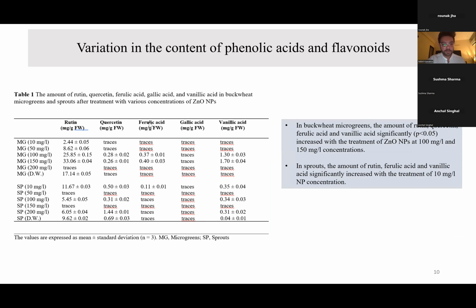After this, ultra-performance liquid chromatography was performed for the analysis of rutin, quercetin, ferulic acid, gallic acid, and vanillic acid. Talking about microgreens first, the amount of rutin, quercetin, ferulic acid, and vanillic acid significantly increased with the treatment of nanoparticles at 100 and 150 mg per liter.